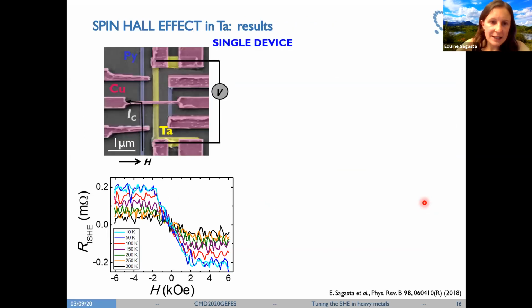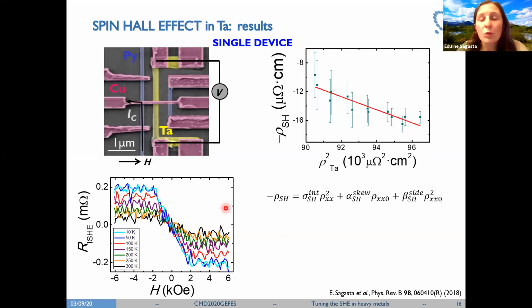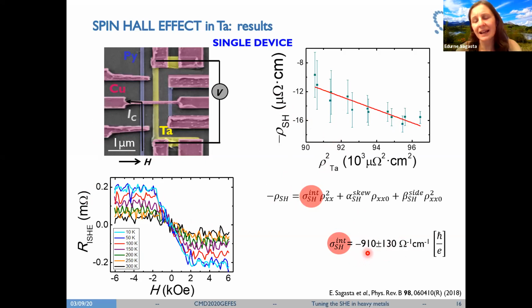So now we will jump to see the results that we obtain in the lateral spin valve. I basically performed, in the same way as I just explained for platinum, the experiments of the inverse spin Hall effect. And here we can see the results as a function of temperature. So in the end, in the same way, we can plot the spin Hall resistivity as a function of the square of tantalum resistivity, so that the slope is giving us again the intrinsic spin Hall conductivity, which is negative for tantalum, and this is in agreement with what is expected theoretically. And we obtain minus 910 ohm^-1 cm^-1 value.